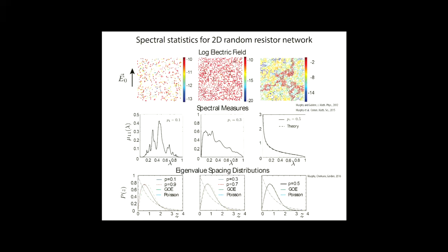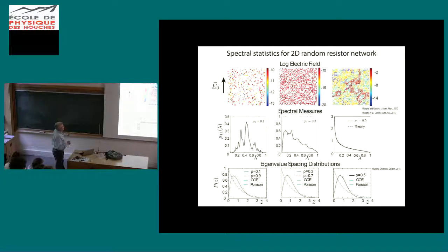And so now we start to get into some of the results in this case. These are just computations of the electric field in resistor networks as we keep increasing the volume fraction. And so these are the examples of the spectral measures in these cases that you can then plug into the measure and get exact representations for the effective parameter. However, because we did the dumb calculation and directly calculated the eigenvalues and eigenvectors, we can then analyze the statistics of the eigenvalues. And so what we found is in very low volume fraction, when the, say, brine inclusions or whatever are all disconnected, you basically have uncorrelated eigenvalues, or their spacings are uncorrelated.